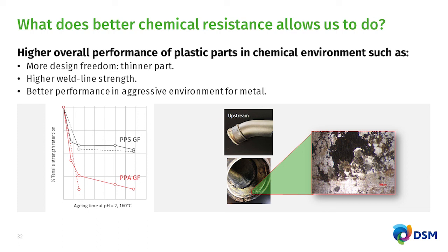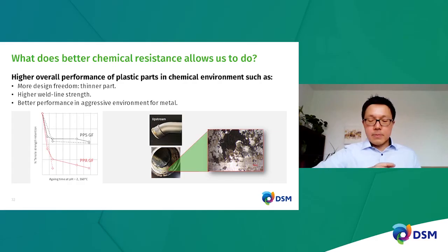And the third one, which is important, which is related to why we use plastic in the first place for automotive, i.e. as a metal replacement, is that time and again, when we do this chemical aging, the chemicals themselves are really aggressive towards metal. By aggressive, I mean corroding, leads to corrosion of metal. So just for example, the right-hand side figure here, this is a type of test that we have been performing where we have a polymer tube with a stainless steel compression ring, and after a certain period of time doing chemical aging, we actually see a lot of corrosion in the stainless steel metal surface, but not so much degradation at the plastic. So it's kind of a reminder that we use plastics to replace metal, but also it brings added value because we are no longer faced by a corrosion issue anymore.